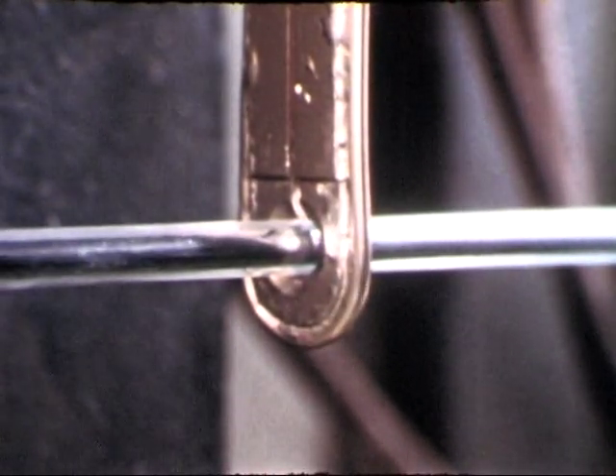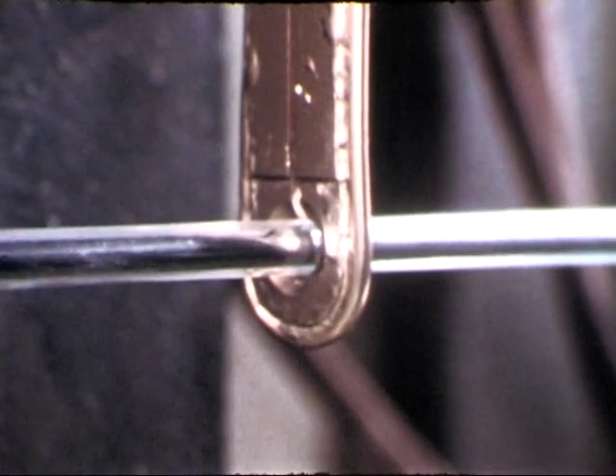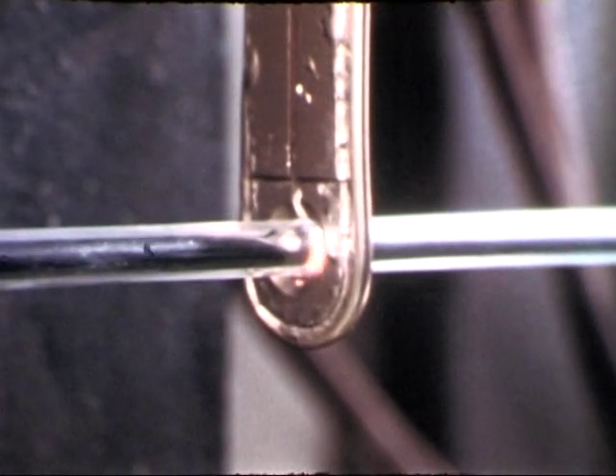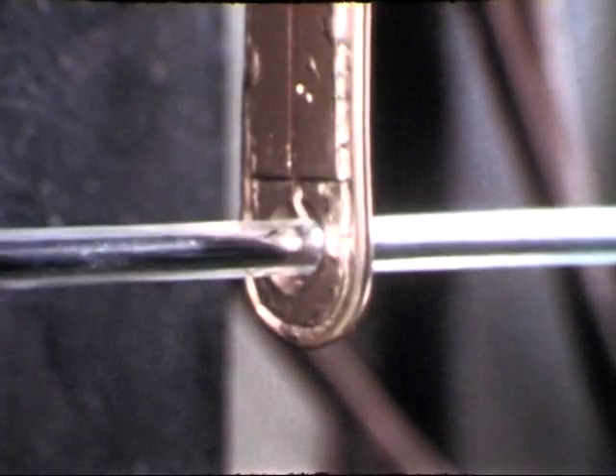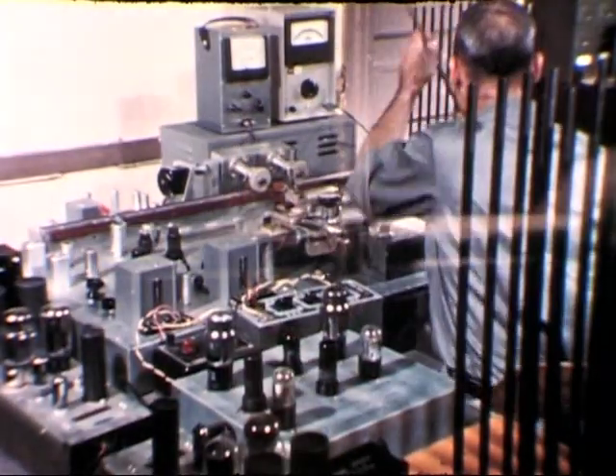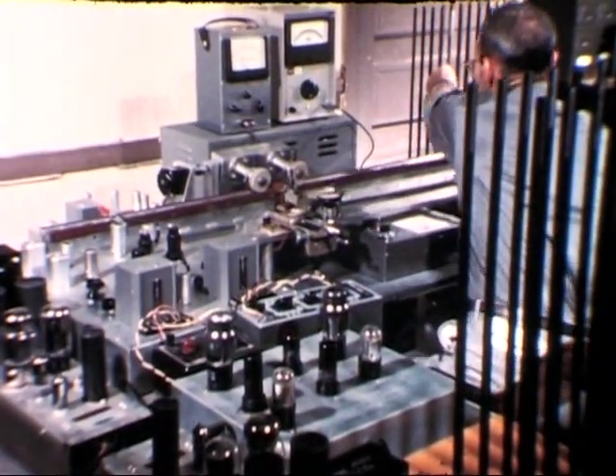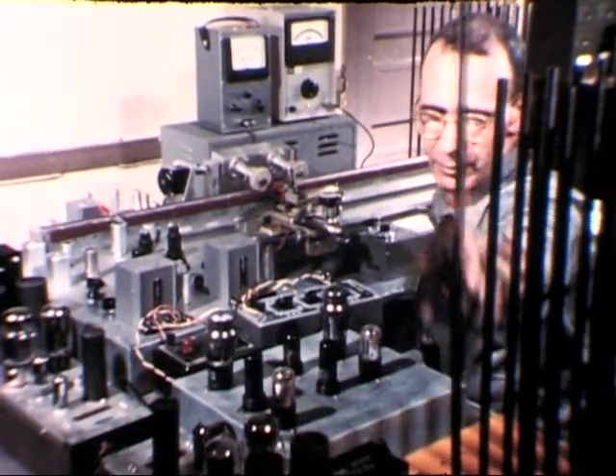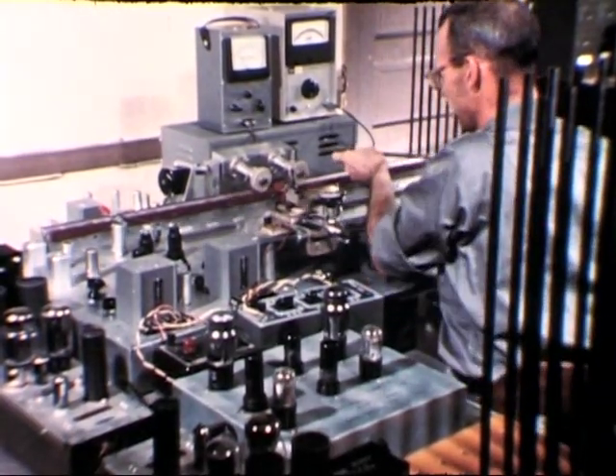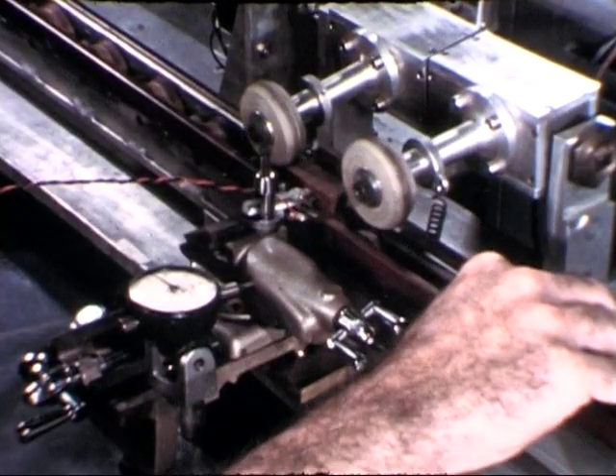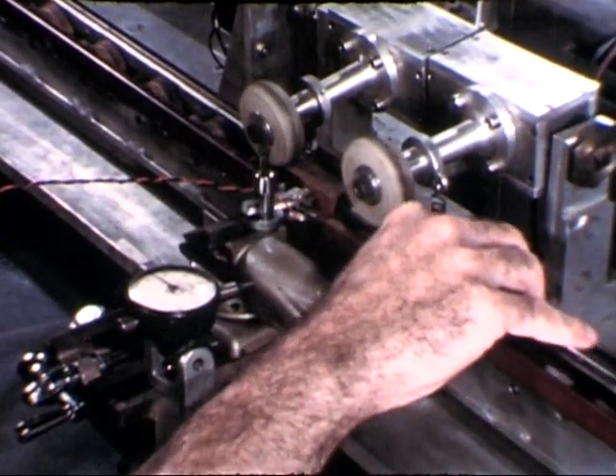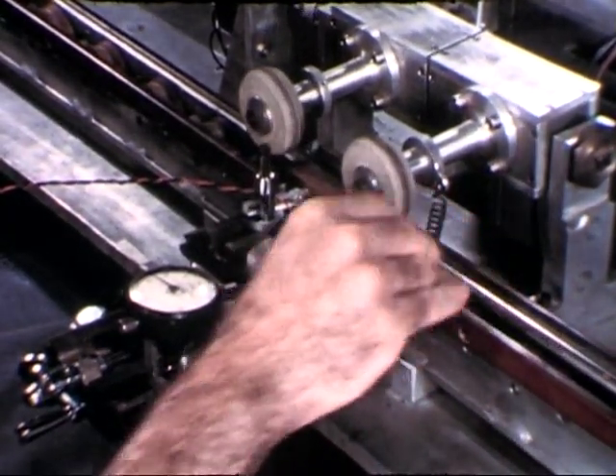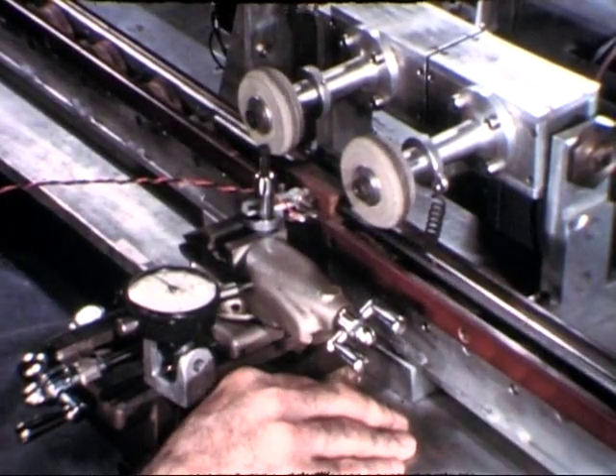The cladding is protected against oxidation by passing a stream of helium through the Vycor tube. After heat treatment, cladding thickness is measured by an eddy current method. Eddy currents are induced in the zircaloy cladding by means of a point probe. The apparent impedance of the probe is influenced by the cladding thickness.